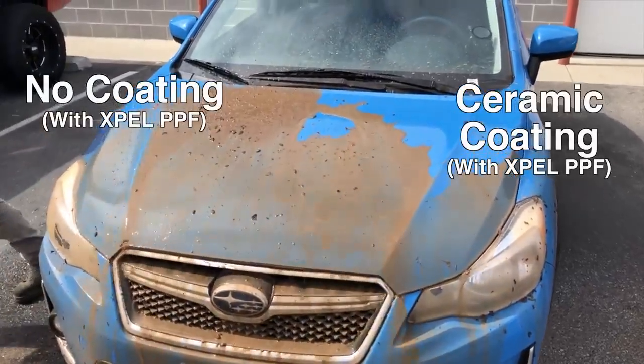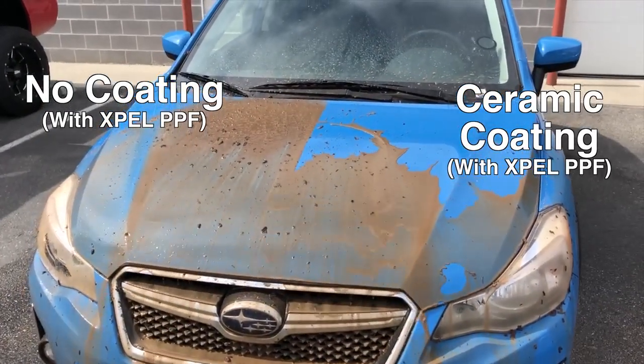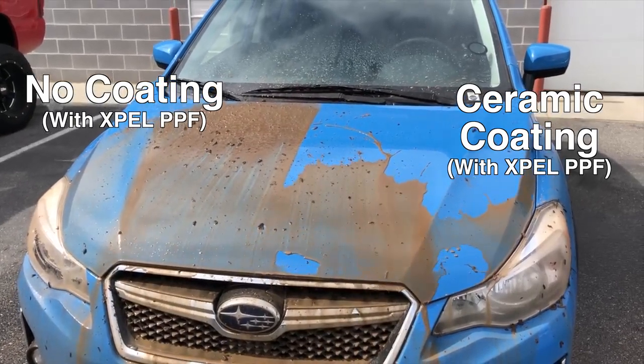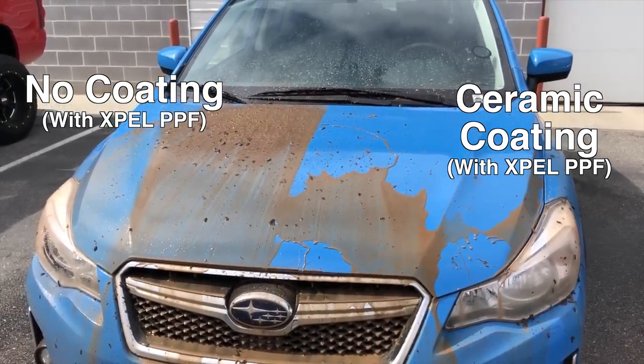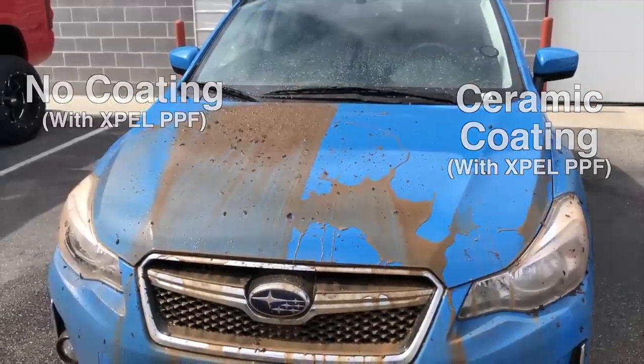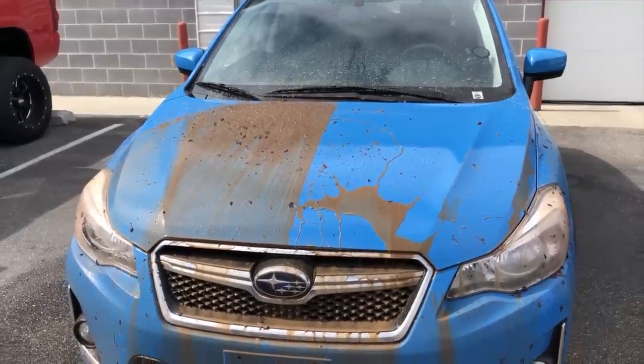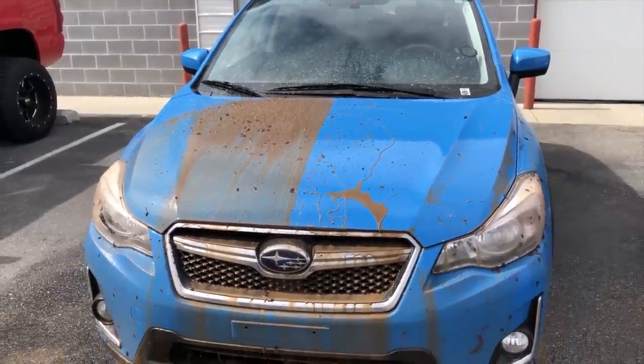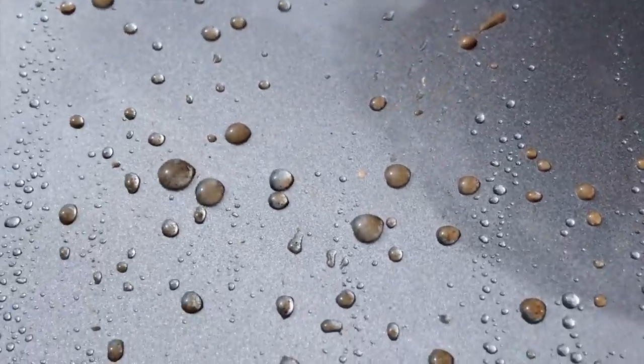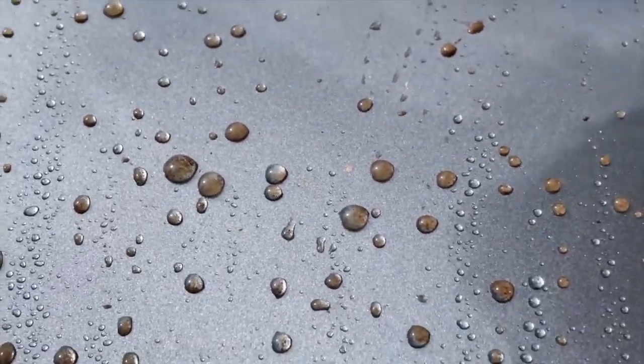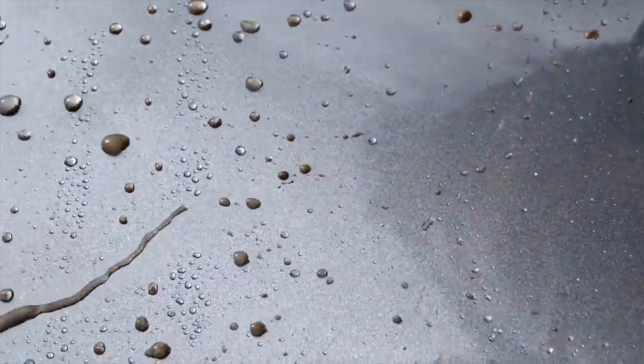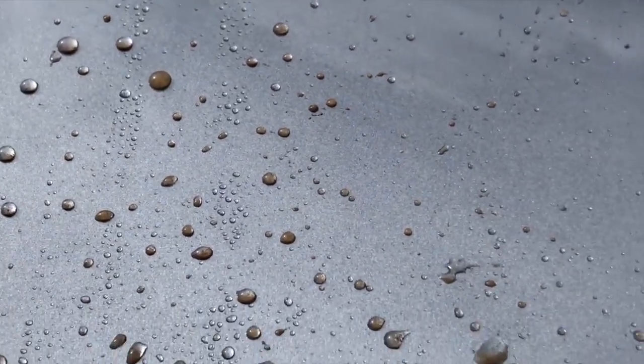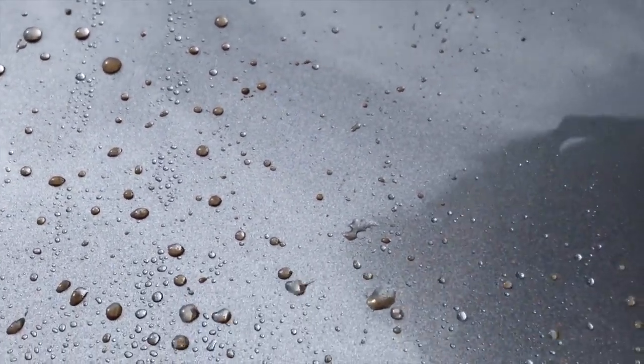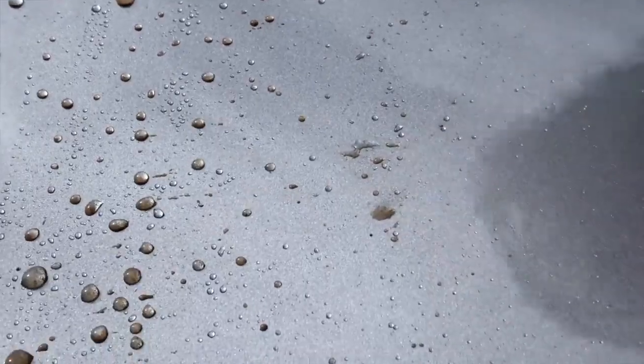As you can see, the ceramic coating on the right side of the hood has significantly less friction and is more hydrophobic. The mud wants to drain right off, whereas the non-coated side keeps the dirt on top. This also illustrates another fascinating property of the ceramic coating, in that it has a self-cleaning characteristic. Dirt on the surface of the car would rather stick to water droplets than the paint surface. So when it rains, dirt traps in the water droplets and is blown off the car as you drive.